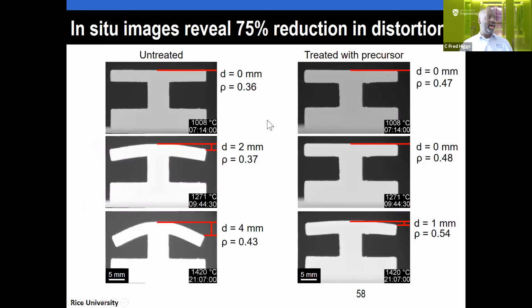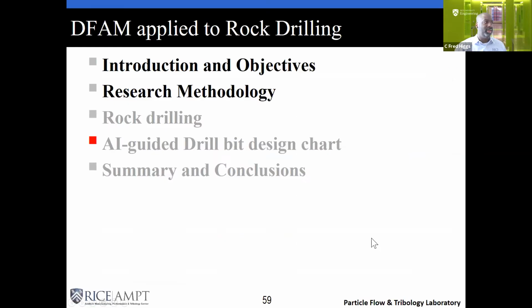And so you have an untreated one, this is what you normally get in binder jet 3D printing if you don't do a smart solution. And companies like X1 and all those have their ways of trying to deal with this. And here's a look at one with our technique where we put in a binder that can turn to solid particles. You do decrease the creep that's there and the distortion that results there.